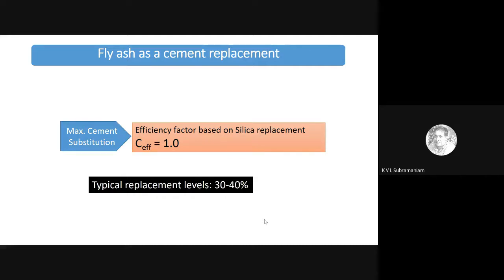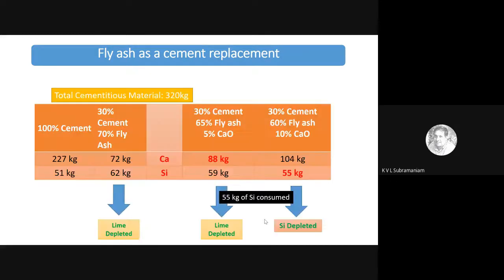So now, using this metric for typical fly ashes in India, we worked out that the typical replacement levels would be anywhere from 30 to 40%. And remember, the code anyway puts a cap on the replacement at about 35%. So this number seems quite reasonable looking at our data.